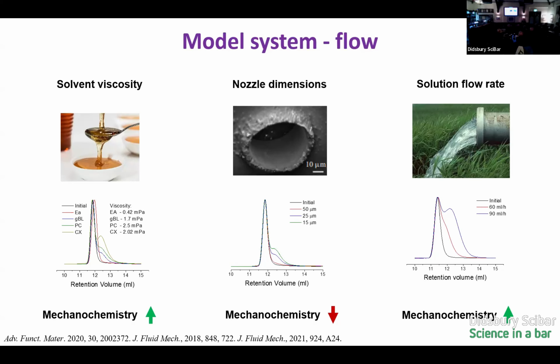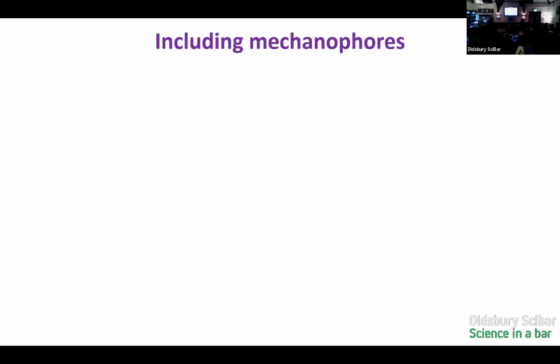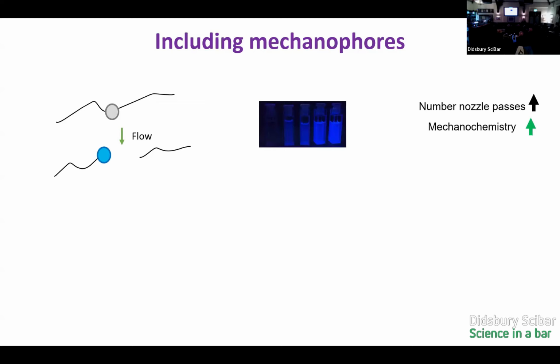And this is all just using PMMA, like I say, an acrylate that's used in all kinds of structural materials all over the place. What happens if we then include a mechanophore? So we started off including a mechanophore that was fluorescent. So we get light given out when it's broken open. And what we see is that we can control effectively the amount of fluorescence, or light, that we get given out by controlling the number of times we pass it through our nozzle. So if we pass it through our nozzle multiple times, we get more and more fluorescence out of the material. And this is if we have a single mechanophore in the middle of the polymer chain.